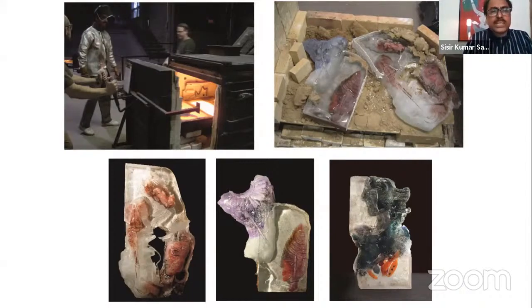Then from the annealing point to the strain point, around 400 degrees centigrade. Then it goes slowly to room temperature. It takes about, for my kind of work, 15 days to 28 or 30 days of annealing cycle. After that, I take it out from the mold. One can see these two pieces, fused, molded and cast, all together. Then finally, this is how they come to life. And after a little bit of polishing and finishing, this is how they look.